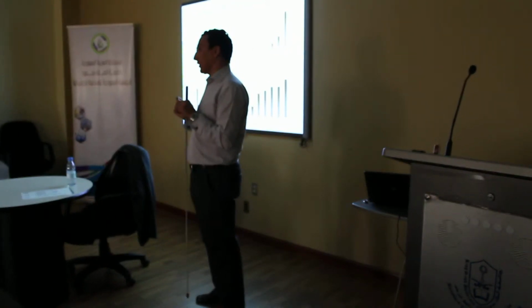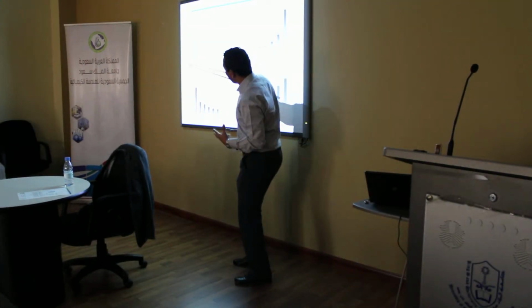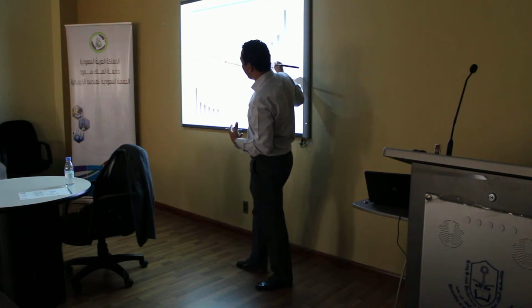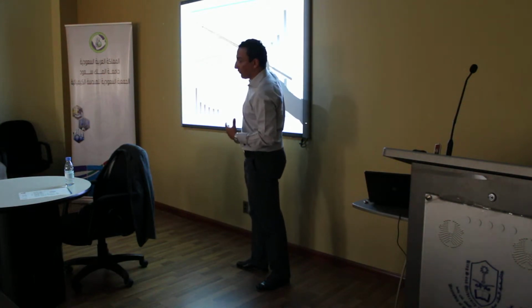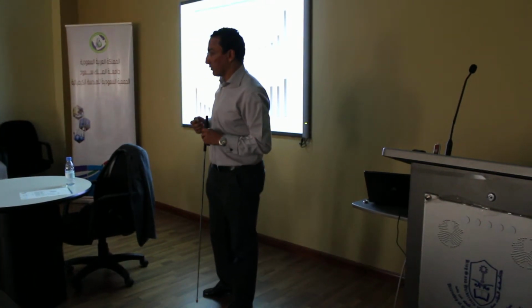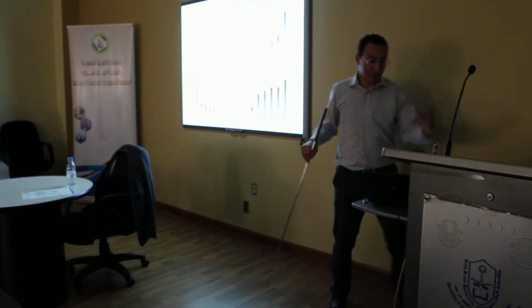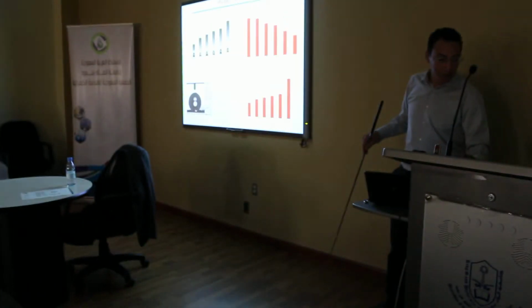We want the membrane to be very thin and with very high mechanical properties. So this is what we observe here. This is the spectra of only PVDF, and these are the spectra of the PVDF mixed with multi-wall carbon nanotubes. So you can see that the mechanical properties improved.